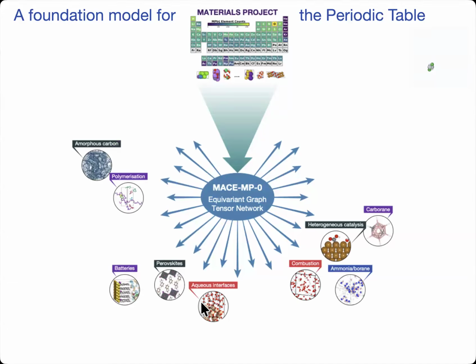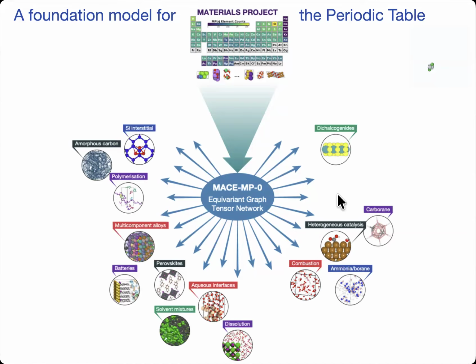And then you take this model and you just simulate whatever material system occurs to you. And my group did that. Every student was told to stop whatever they were doing and take whatever structure was on their computer screen and simulate that. So we have simulation of battery electrodes in contact with electrolyte, copper, graphite, flakes, and so on, to perovskites, to aqueous interfaces, of salts to polymerization of sulfur rings, amorphous carbon, combustion of hydrogen, heterogeneous catalysis, and so on, anything that you can think of.